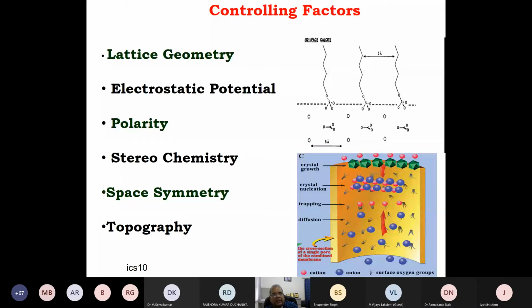There should be matching in the electrostatic potentials. There should be matching of the polarity. There should be a matching in the stereochemistry, space symmetry, and topography. Suppose if all these 6 parameters match, you can create a nature-like control in your materials lab, but that is damn difficult. If you can have 2 or 3 controls, or say 3 controls, you can have a very much controlled process for the synthesis of nanomaterial.